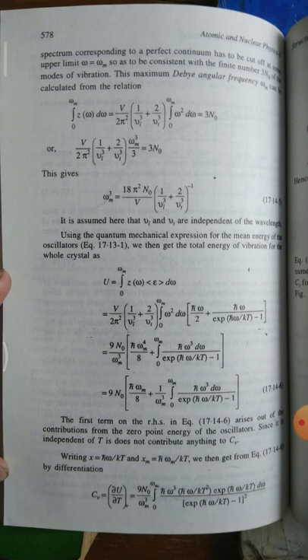The maximum Debye angular frequency ω_m can be calculated from the relation: integration 0 to ω_m of z(ω)dω = V/2π² (1/v_l³ + 2/v_t³) integration 0 to ω_m of ω² dω = 3N₀. So V/2π² (1/v_l³ + 2/v_t³) ω_m³/3 = 3N₀, giving ω_m³ = 18π²N₀/V (1/v_l³ + 2/v_t³)⁻¹. It is assumed here that v_l and v_t are independent of the wavelength.